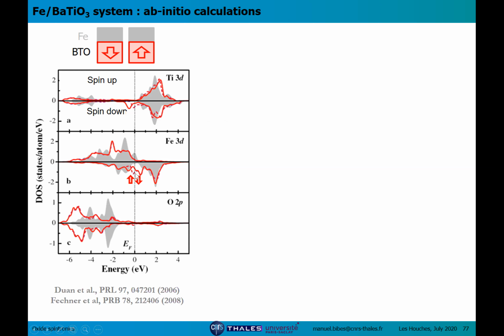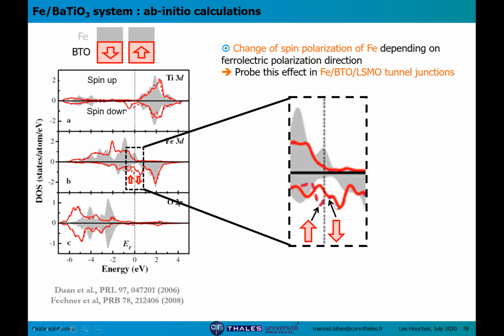So you see that you have finite spin polarization of iron, of course, but it depends on the ferroelectric state. Okay, if the BTO is pointing towards or away from the iron, the density of states is modified. This is shown here in this highlight.